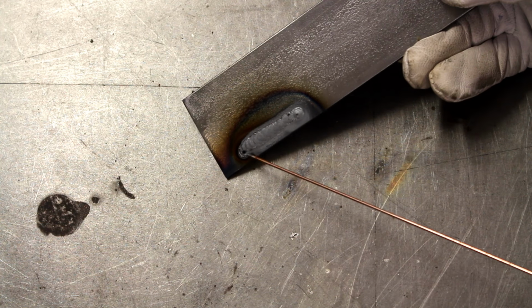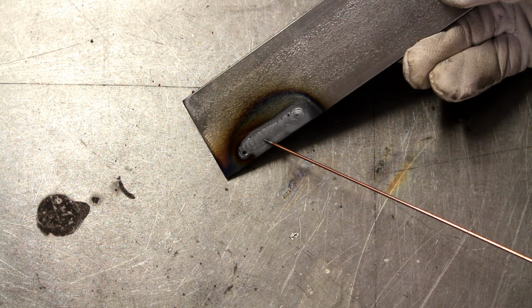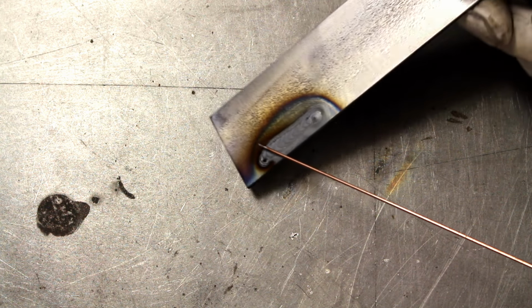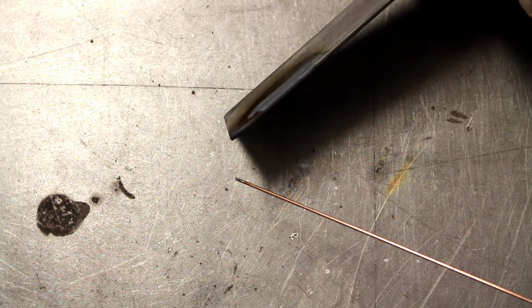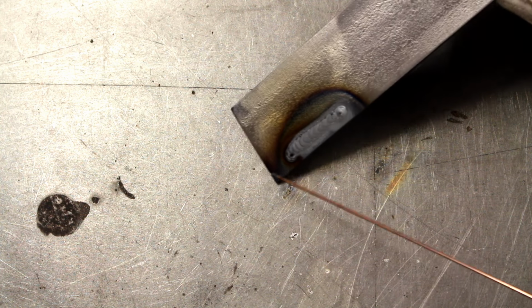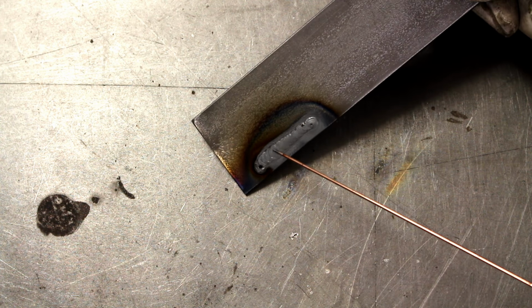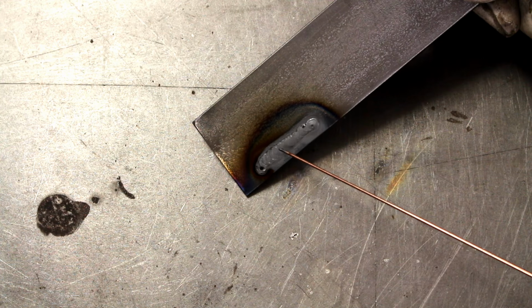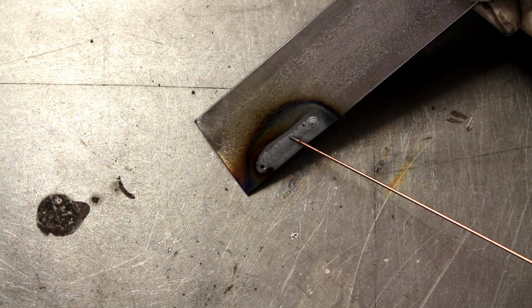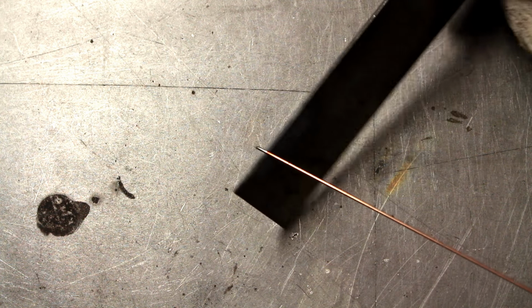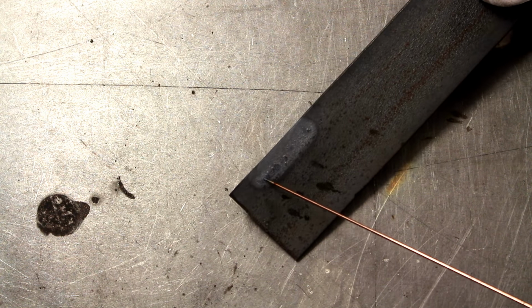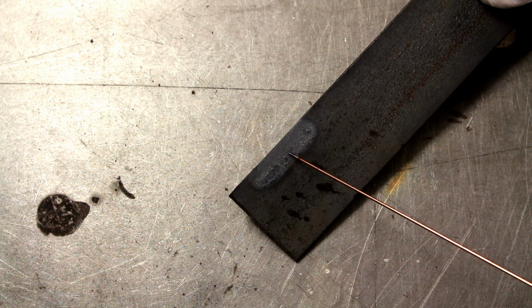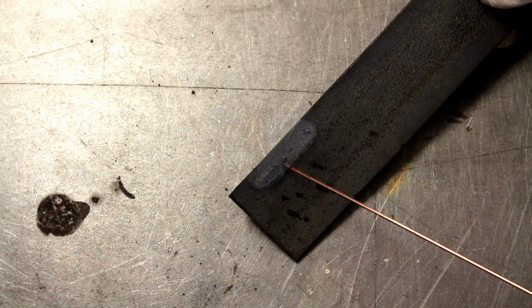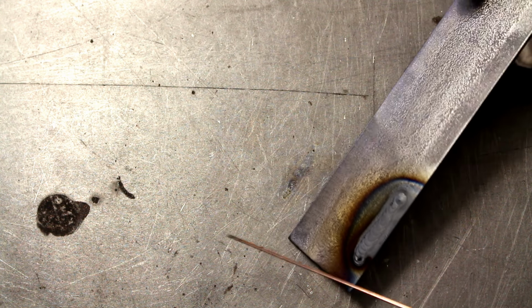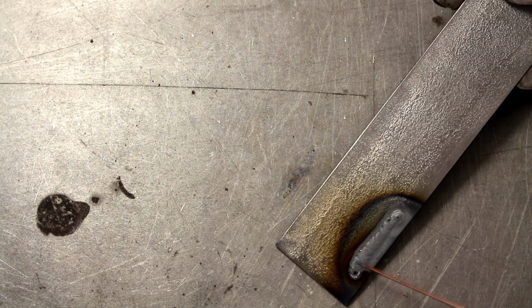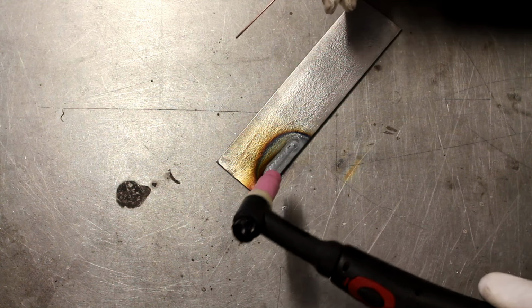Okay, you can see the weld beads where I've added the filler rod. Now this bead is very flat. If you look almost on side view, it's pretty much flat. So I would be turning the heat down on this job because there's probably too much heat. And if we flip it over, you can see it's starting to penetrate through the back of the plate here. So, okay for the exercise, but I would dial the heat back if I was going to continue this.